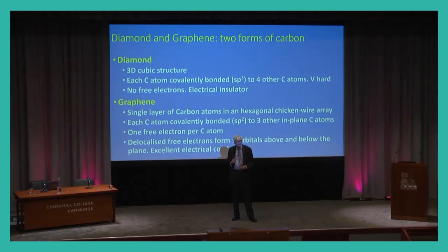On the other hand, graphene is very different, although it's just composed of carbon atoms. It's a single layer of carbon atoms in this chicken wire array. Each carbon atom in graphene has what's called sp2 bonding to three other in-plane carbon atoms. So diamond sp3, graphene sp2, so there's an electron left over, and those electrons float above and below this carbon plane, and they're delocalized, called pi orbitals, and so they're free to move easily. So graphene is an excellent electrical conductor, whereas diamond is an electrical insulator. Although diamond and graphene have exactly the same element, carbon, it's the bonding which is responsible for their properties.